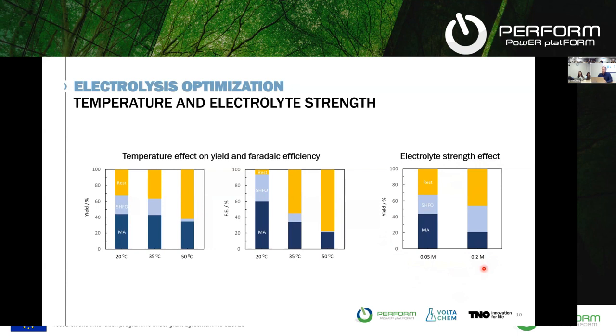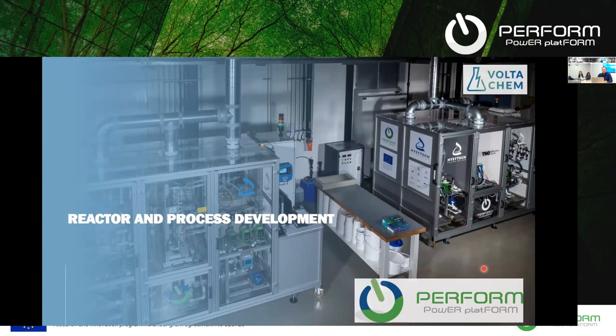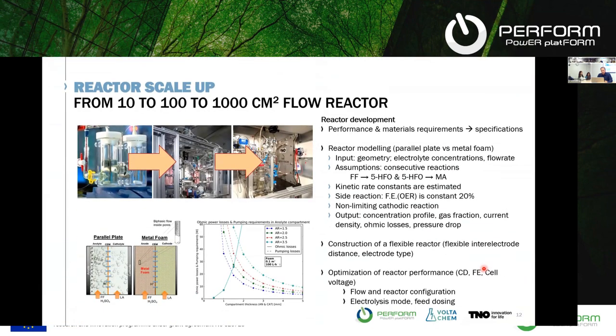like an H cell or a smaller 10 square centimeter flow cell, then you have sufficient information to move to the next step. And the next step is indeed scaling up from these tiny setups to bigger setups where different parameters come into play. For example, now you have a flow cell that has a certain geometry. You need to optimize the geometry a bit. You need to optimize the electrodes that you want to put in, whether you use plates or metallic foams, and the thickness between the anode and cathode. All these parameters become really relevant in this intermediate phase to then be able to scale up even further.